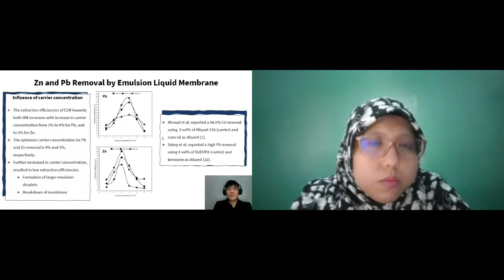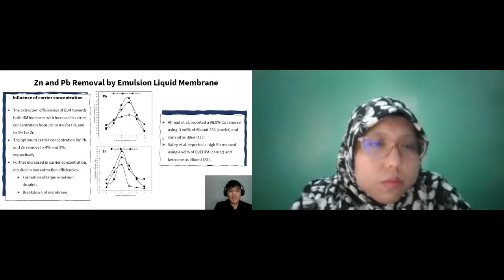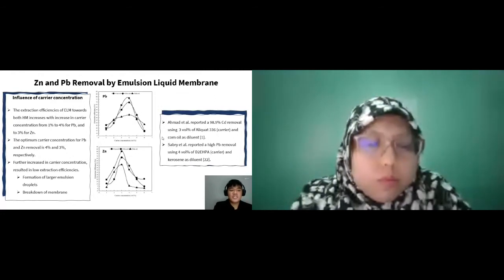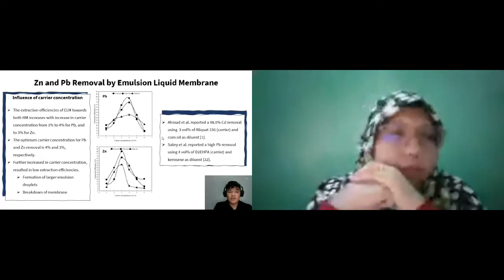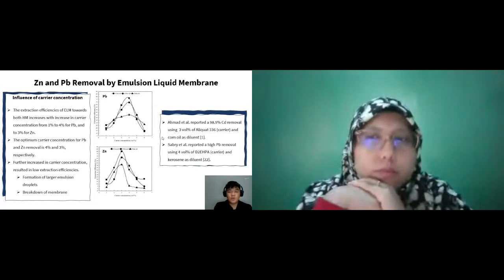The graph shows the extraction efficiencies of these heavy metals increase with increase in carrier concentration. However, as we increase the carrier concentration further than the optimum value, which is 4 volume% for Pb and 3 volume% for zinc, the extraction efficiencies decrease. As carrier concentration increases, it is said that large droplets of emulsion start to form due to the enhancement of ionic charge on the droplets of the emulsions. Larger droplets will have smaller interfacial area, which results in less diffusion of solute across the membrane.